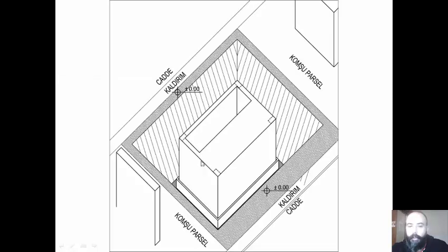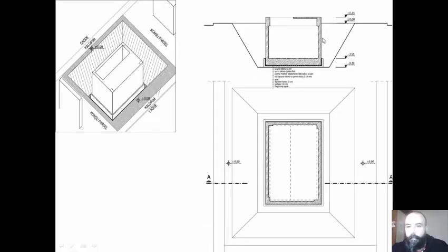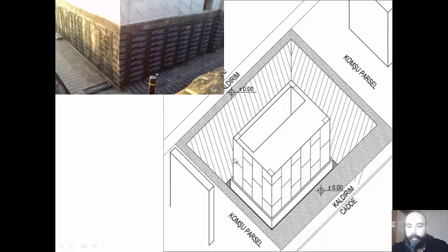So we have the earth, and then this 10 centimeter thick concrete pool with leveling concrete, and undercoat the liquid bitumen. After that we have polymer modified elastomeric bitumen waterproofing membrane, 2 layers of 4 millimeters here, and we have a polyethylene film, this separation layer, and we need to protect all this system with protection screen. After that we can do our reinforced concrete work with raft slab and shear walls, and ground floor level with grade beams here.